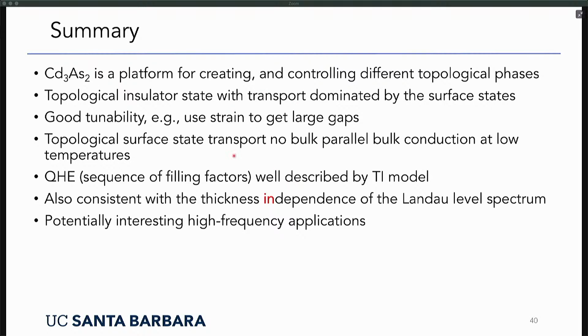Just mention a few of the points I was trying to make. What I wanted to show you is that cadmium arsenide is a very good platform for creating different topological phases, each of which is of interest for different types of applications, which I couldn't get to. We actually get a very good topological insulator state with transport that is really only through the surface state. So unlike some other candidates for topological insulators, where the bulk was not very insulating, and you got mixed transport through both surface states and the bulk in electrical transport measurements, this is not the case here. So it's really quite a good topological insulator once you open a band gap.